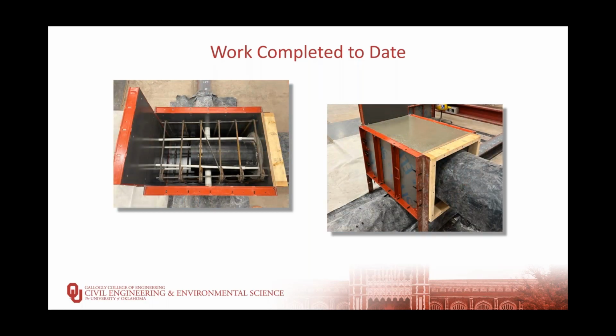We then designed and installed the loading stub for the first column, including plasma cutting a hole in the inner steel shell so that we could place our 2-inch diameter threaded rod through the column, anchoring it to the loading stub and attaching it to the hydraulic actuator to apply the load. We also extended the PVC ducts through which we were going to place pre-stressing strand to provide our constant axial load during the test, and then installed a fairly light reinforcing cage and then placed the concrete for the loading stub.